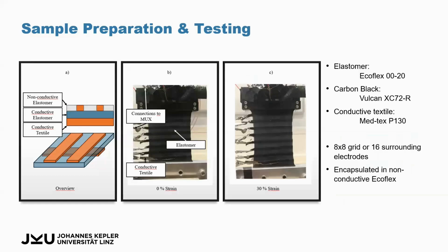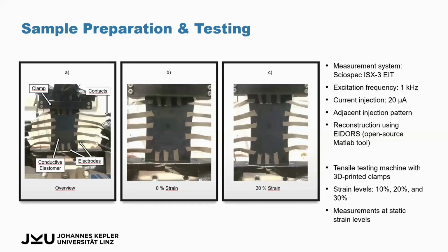For the grid-based sensor, we opted for very conductive textile electrodes. This is a silver-based conductive knit, very stretchable, so we don't really interfere with the stretchability, and this can easily stretch to 30% or more. It's all encapsulated in a non-conductive matrix, and we have an 8x8 grid sensor. The grid-based approach has the advantage that, in comparison to single sensor nodes, the number of electrodes or connections scales by m plus n instead of m times n if you go for large area sensors. And we put that in the tensile testing machine and strained it at various strain rates.